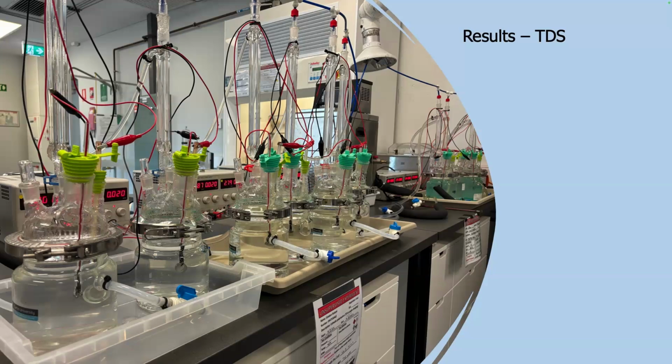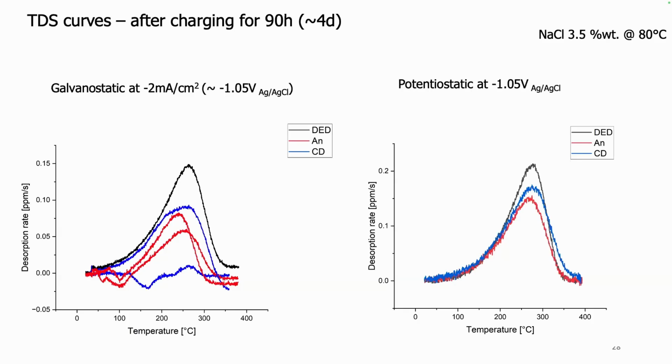But there is one problem: it is 20 millimeter diameter, 70 microns thickness, so there's a lot of area, not too much volume. So when we did the charging, we started charging galvanostatically because we need to charge many samples. And then the profiles were not good.